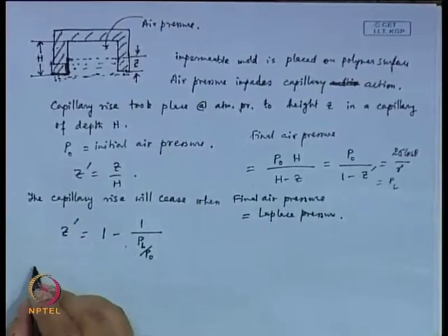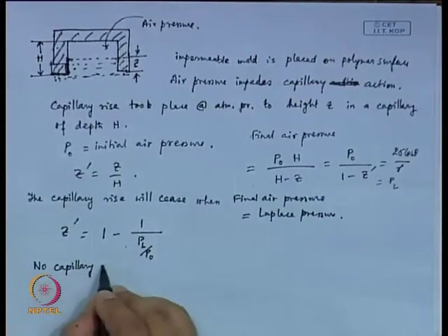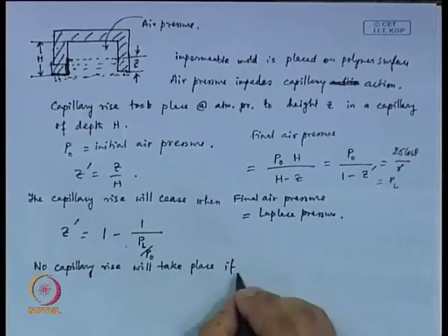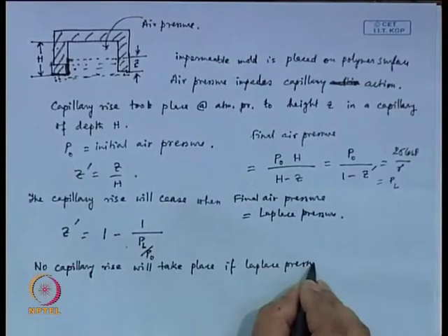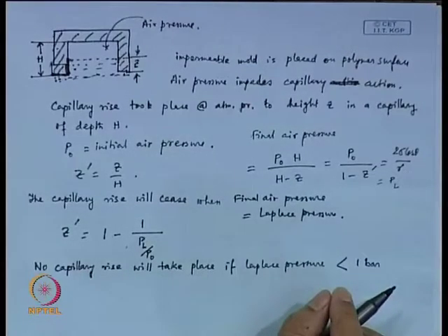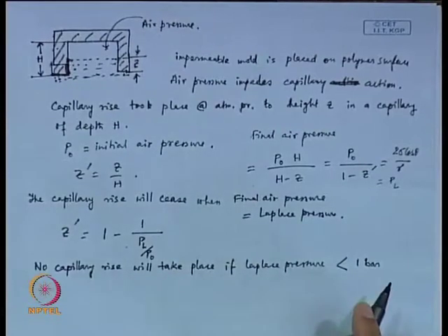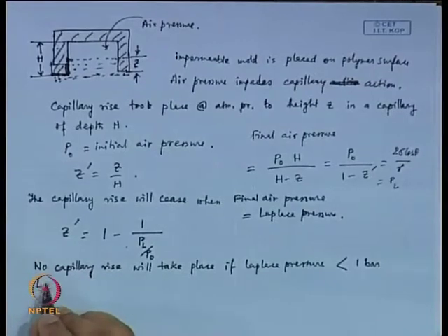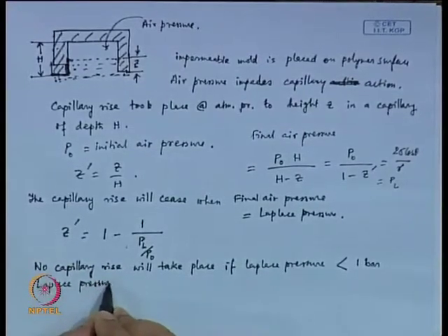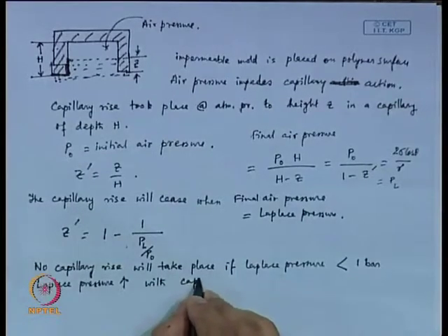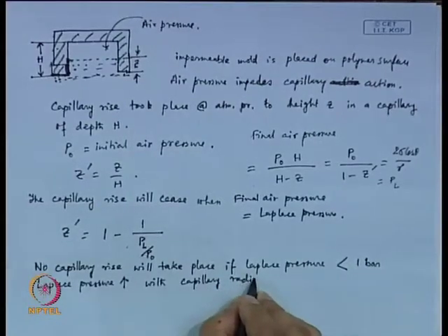Now, you need to understand a couple of things here. No capillary rise will take place if Laplace pressure is less than 1 bar, less than atmospheric pressure. If it is less than atmospheric pressure, no capillary rise will take place. That is one issue here. Second point is that Laplace pressure increases with capillary size, with capillary radius decreasing.